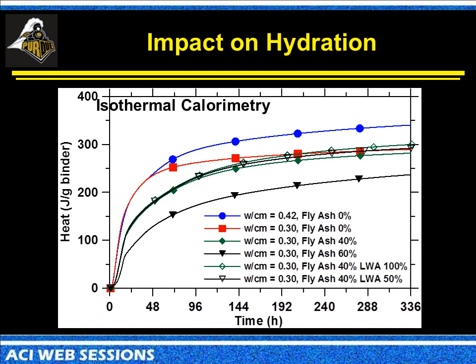If you add water on top of the cell, you'll see that the hydration rate will start to pick up again. As we go from the 0.3, we'll start to see the effect of fly ash. We see that there's a slower reaction, so we see a delay in the amount of heat generation. But when you start to look at these systems here, again, same system, the only difference between the solid symbols and the open symbols is the amount of internal curing water that we're putting into the system. So when we add in internal curing water, we're seeing more hydration taking place in the system. We're more efficiently using the cement that's inside of the overall system.